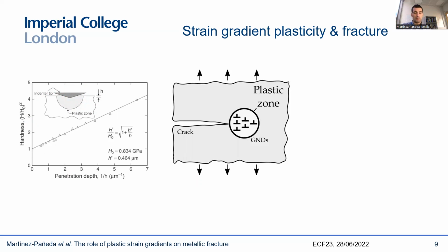The implication that results from this is that no matter the size of your sample, whenever you have a crack, you're typically going to have a plastic zone that is physically small, and that therefore will contain strong spatial gradients of deformation and a very significant GND dislocation density.